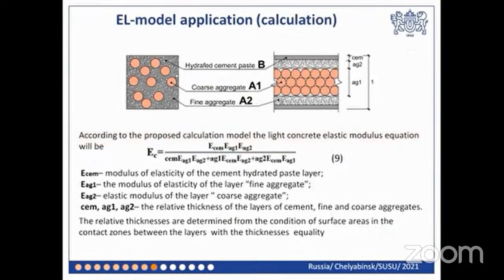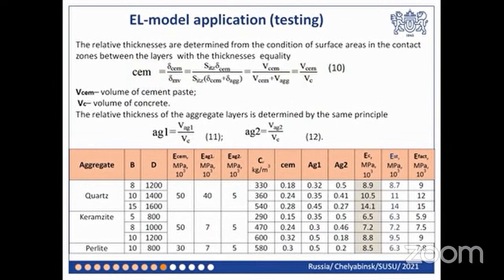Here is presented the calculation EL model as a pack of elastic layers where ITZ is accepted because its properties are equal to the binder. According to the proposed calculation model, the light concrete elastic modulus equation includes factors of aggregates and binders elasticity models and related thicknesses. Their calculation algorithms are suggested too. Compositions of light concrete mixes of our own concrete mixing plant of demanded classes were used for testing. The table shows the calculation and testing result of the elastic modulus of light concretes. Calculated and actual results differ by not more than 10%.